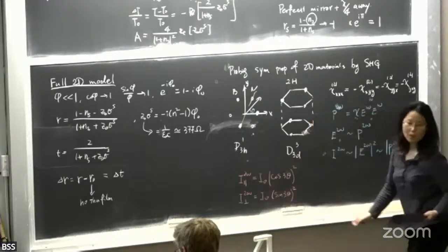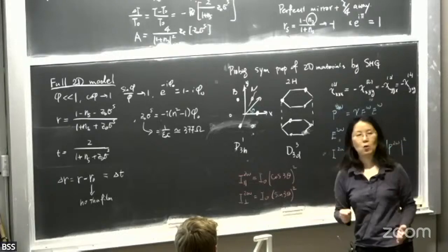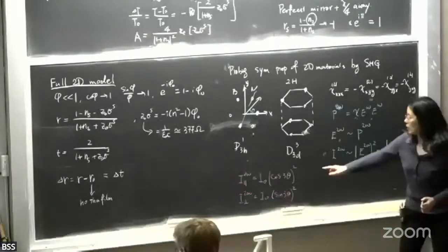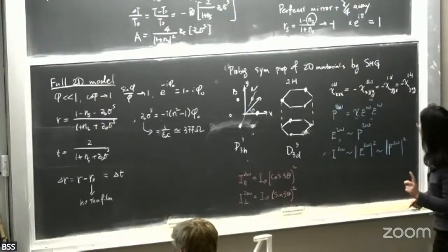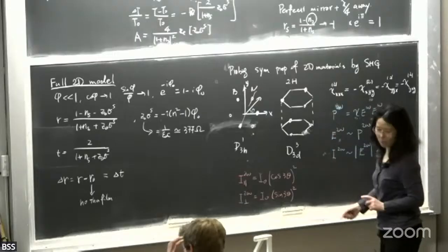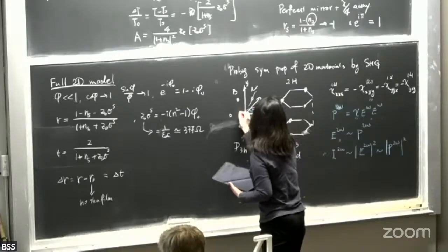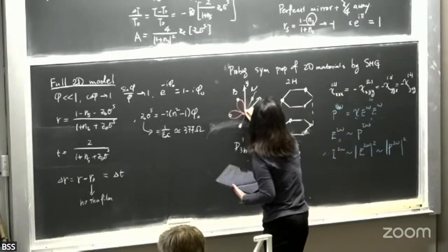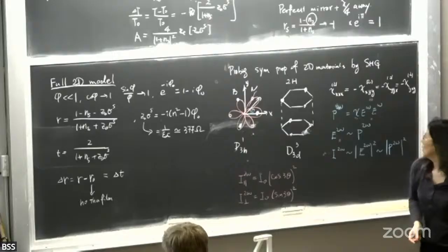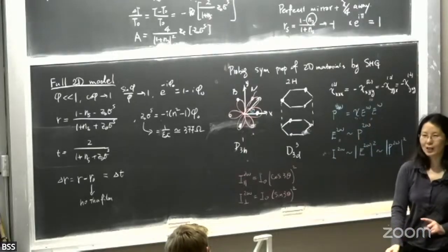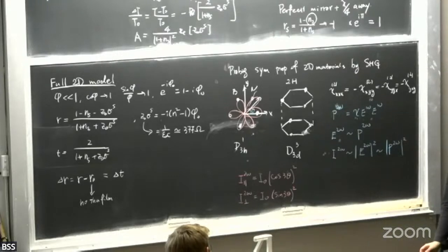This 3 theta should not be too surprising if you look at the structure. You get 6-fold, and 6-fold is because we are looking at the intensity, so the field is 3-fold degenerate. If I draw the pattern on top of it, you get this beautiful flower type pattern, like this. Experimental results actually are more beautiful than what I put there.